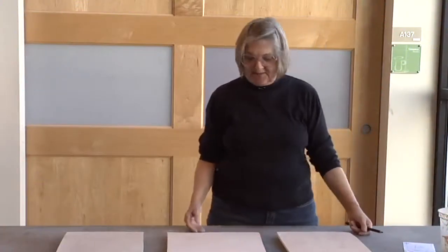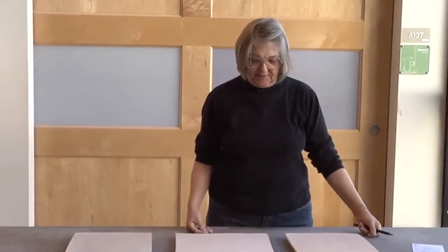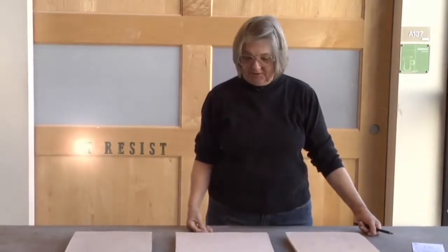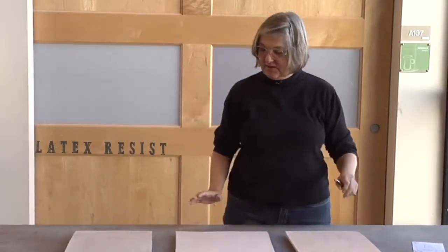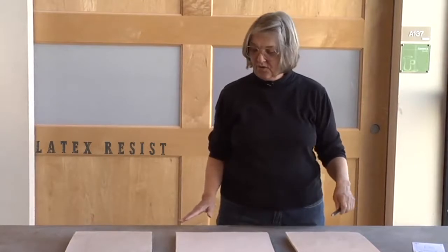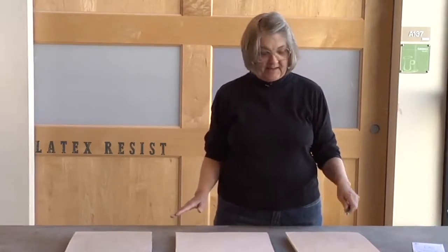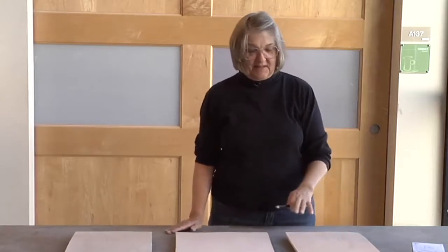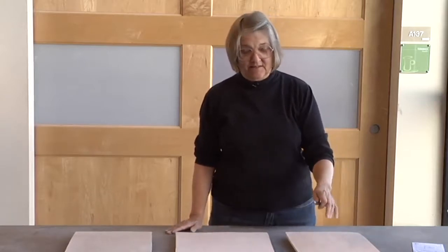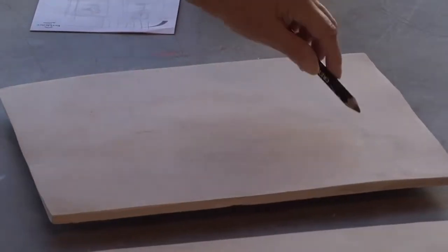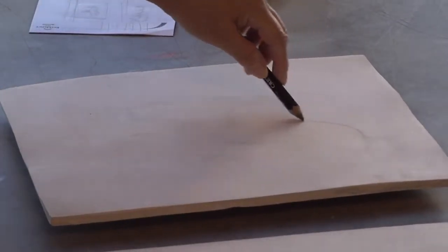I'm going to be decorating some slabs for raku, and I'm going to be using the latex resist. So the first thing I do is to make a drawing on each slab, and then I'll go back and fill it in with latex. Then when the latex dries, I'll glaze it, pull the latex off, and go back in and decorate with a luster line for the raku firing. So right now I'm just going to do a horse.